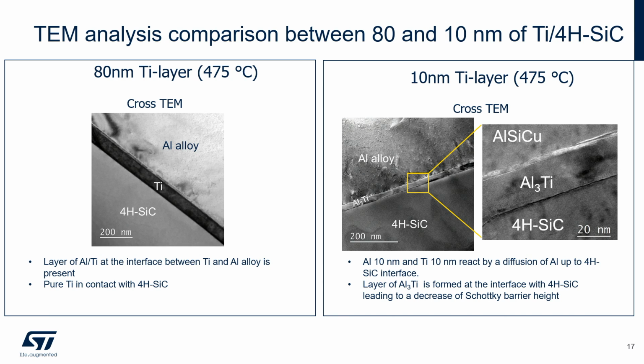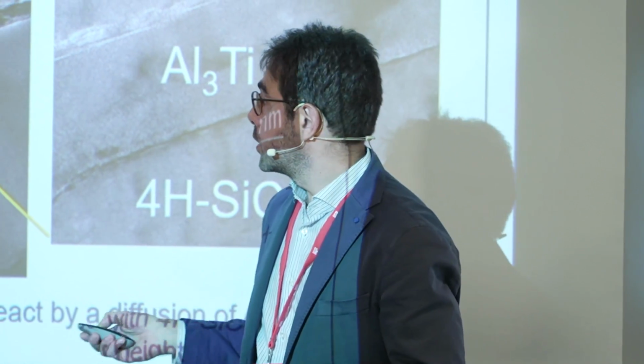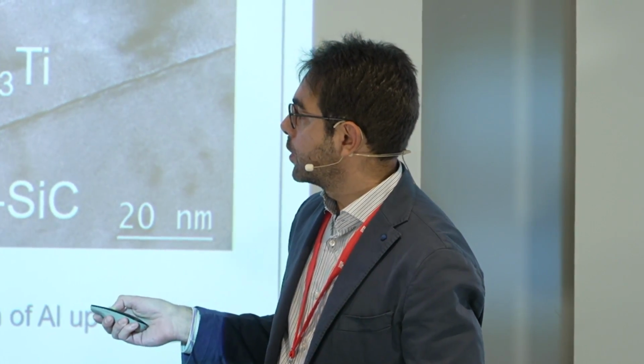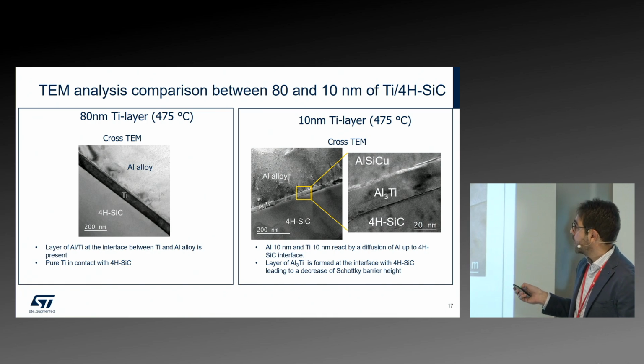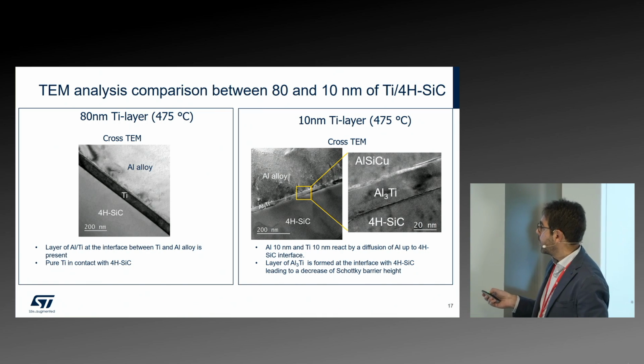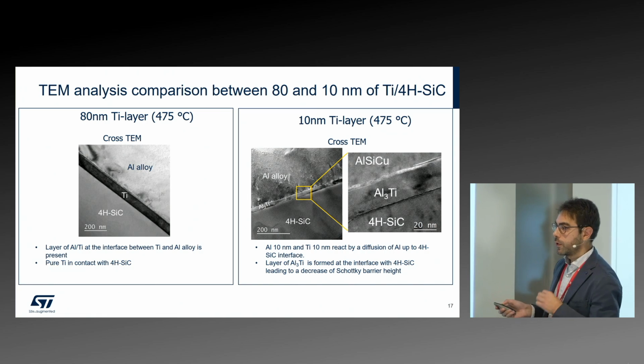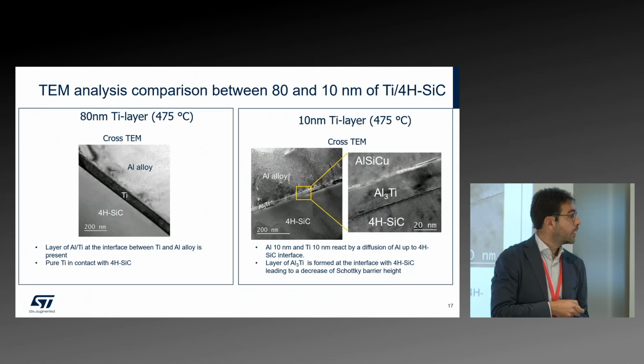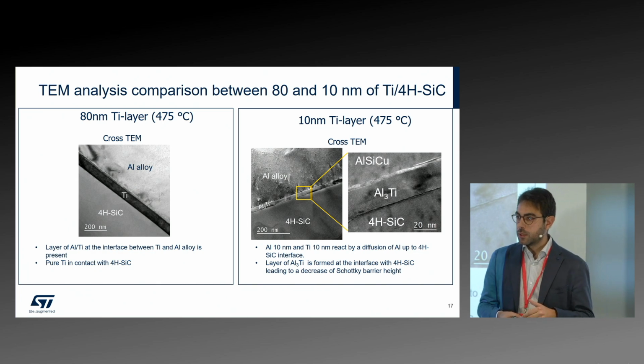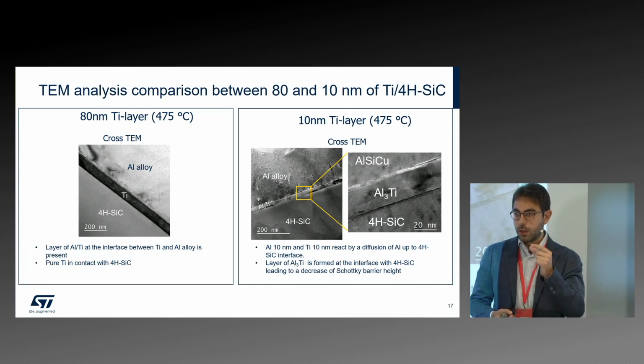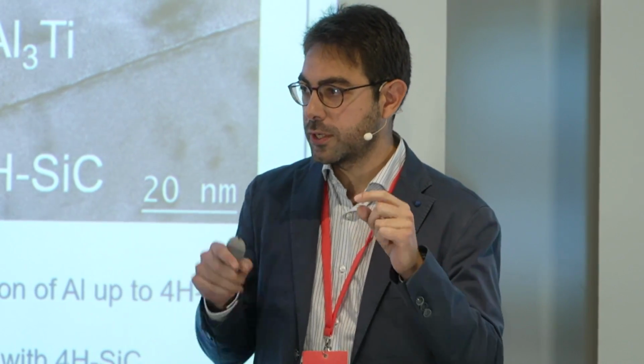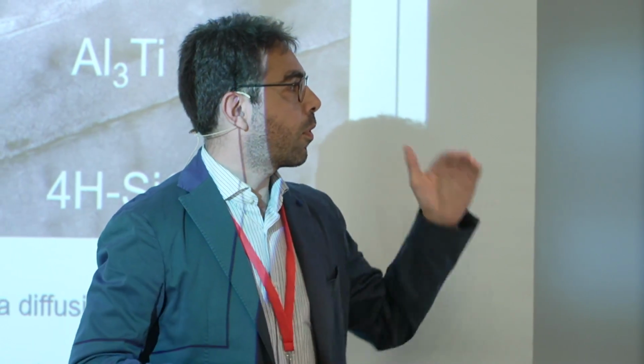So what we thought is, what happens if I grow just 10 nanometers of titanium and put aluminum on top? Aluminum should arrive at the surface. And this is the case, because aluminum arrived there and reacts with titanium. Here there is a higher magnification, and it forms a titanium compound in a very homogeneous way. This is all crystalline, so very homogeneous, very good quality of my Schottky contact, and it showed a 0.9 barrier height. So just by changing the thickness of my Schottky metal, in this case titanium, the process flow doesn't change; I just sputter not 80 but 10 nanometers. I lowered the barrier from 1.2 to 0.9.